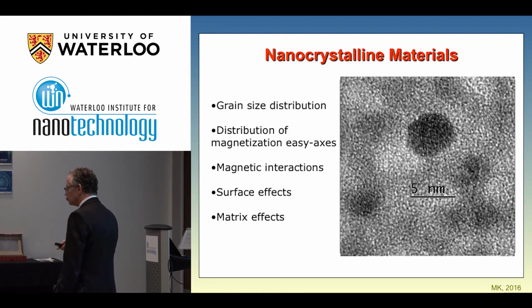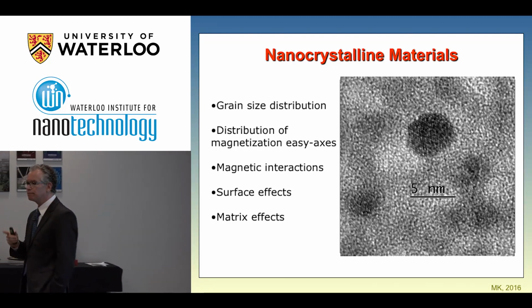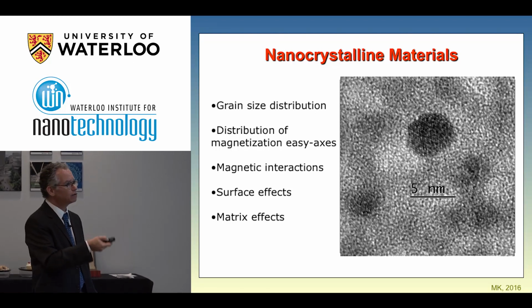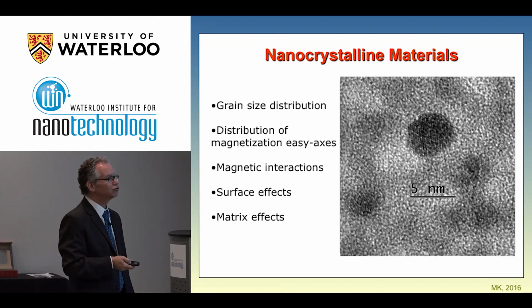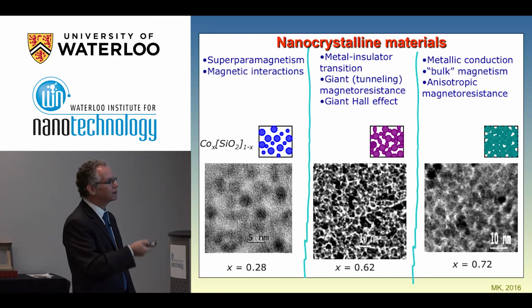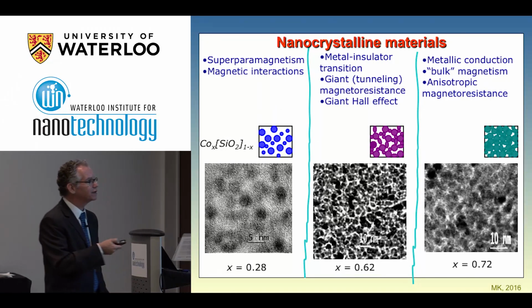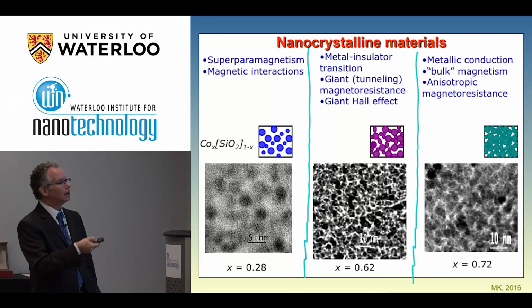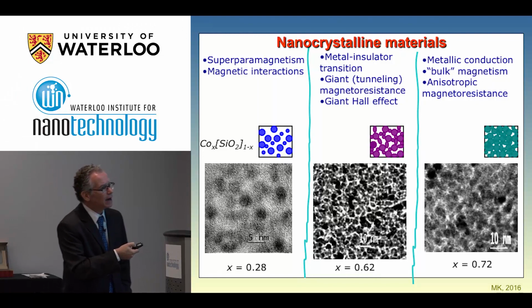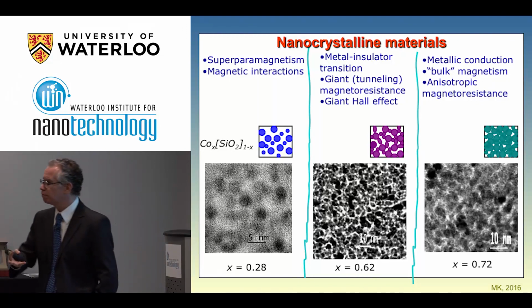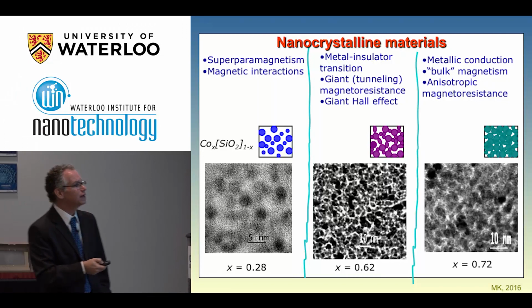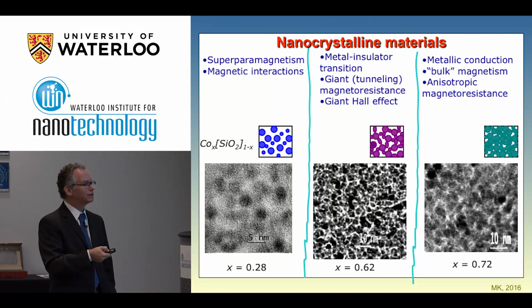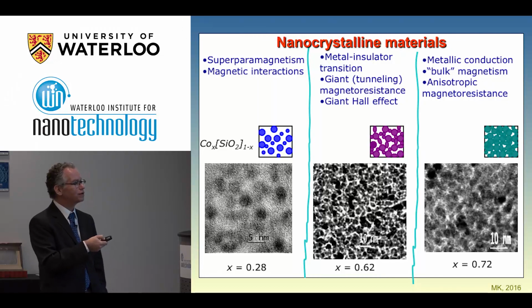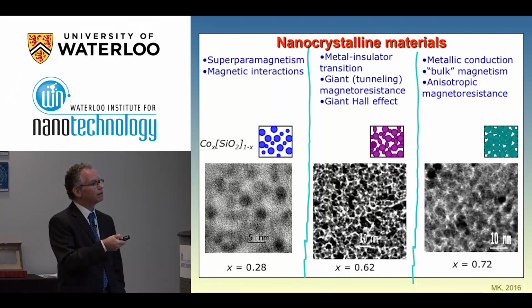So we have not only extremely important technological challenges, but we have also some basic challenges that we would like to understand a little bit more. So I work, as I mentioned, with this kind of systems, granular systems, and in this example, you have already an idea that this is a very interesting playground to work around. So this is simply a sputtered sample. You can have, just by changing the composition of cobalt in a silicon oxide matrix, you can have different regimes.